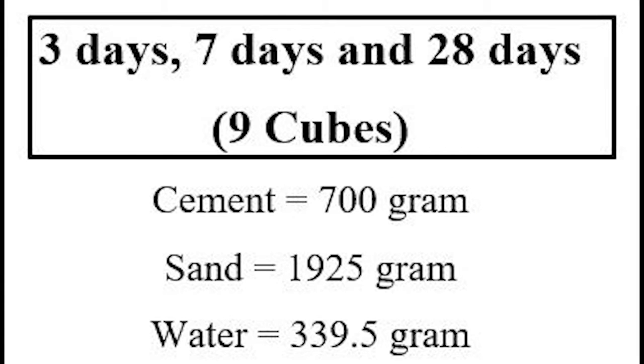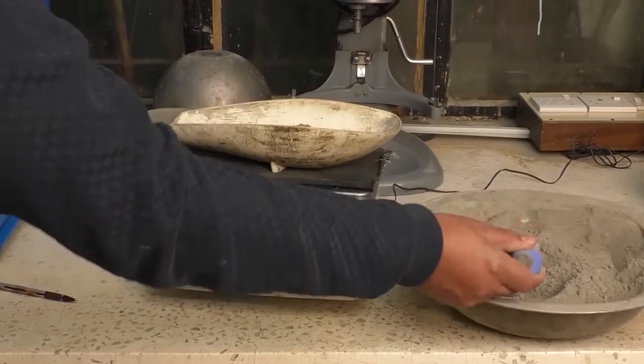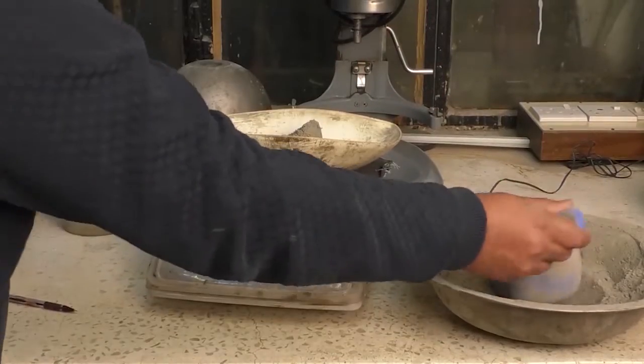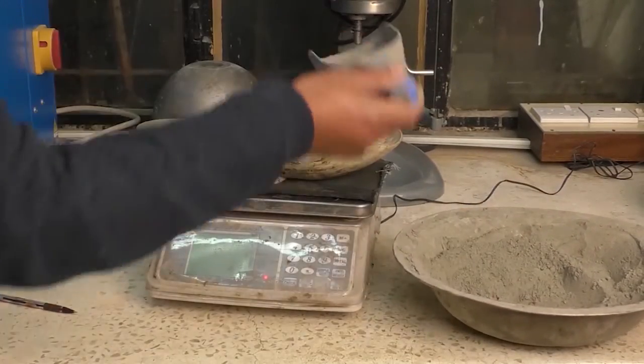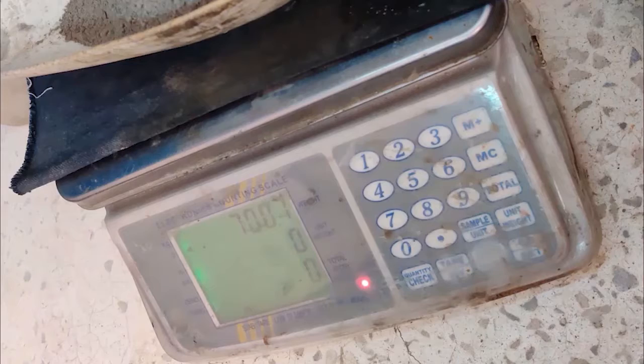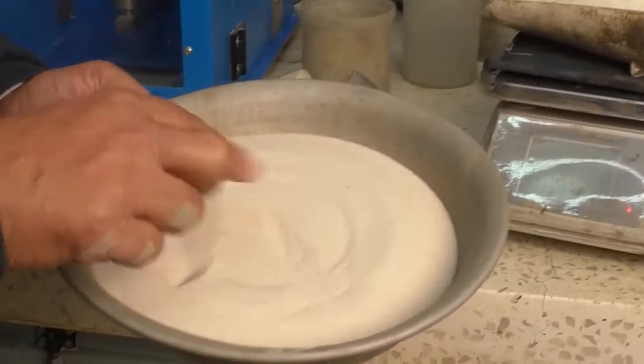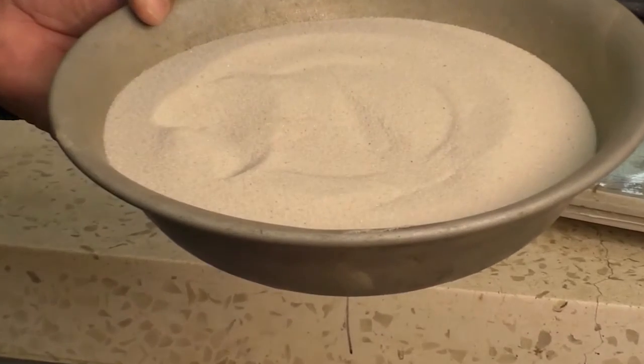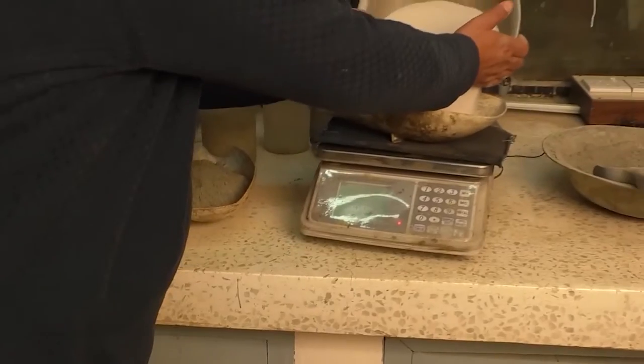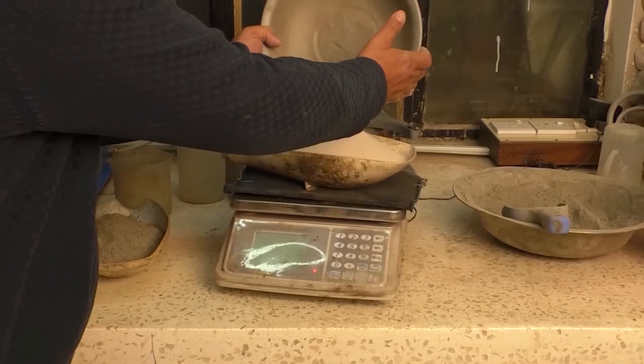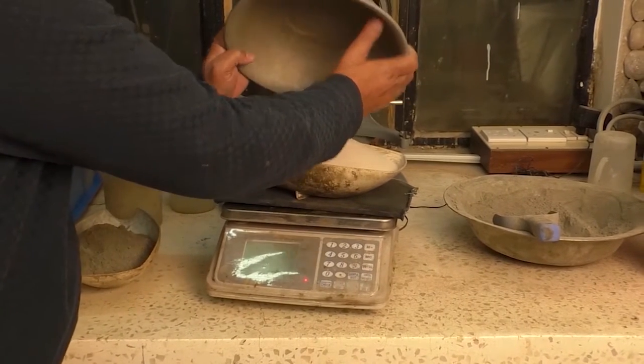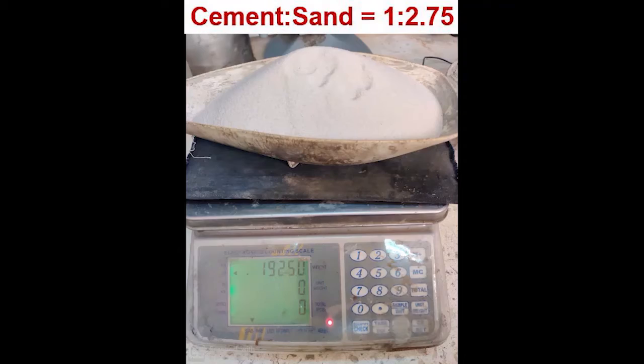We will be making 3 specimens from a batch of mortar for each period of test, that is 9 cube specimens. As you can see from the video, we are taking about 700 gram of cement to prepare our cement mortar cubes. The sand used in this experiment is Ottawa sand having a gradation as per specification of C778. Now we are taking about 1925 gram of sand for the mixture.